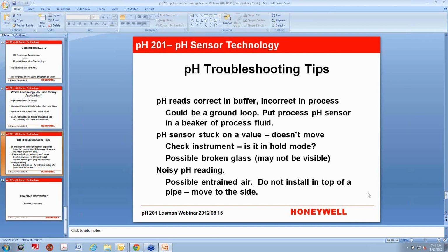You can't always see broken glass. If you have a sensor that you have threaded into line and somebody has used a pair of channel locks on it to tighten it or to loosen it, that twisting motion can cause the glass stem that runs the length of the sensor to get a tiny crack in it. You'll never see it because it's inside the sensor, but over a small amount of time it will create a liquid path between the reference, which surrounds it, and inside the glass where the measuring electrode is. And when that happens, it usually sticks on something. So you don't want to ever use channel locks on your pH sensors unless you're just taking it out to throw it away.